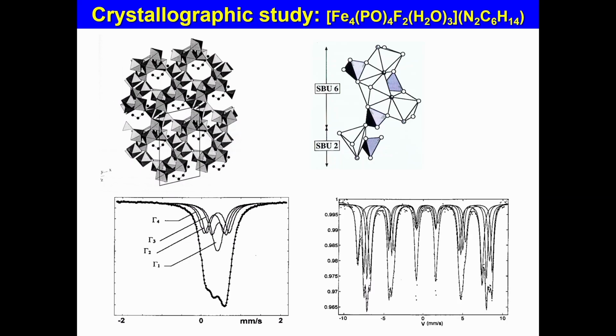Now, some spectra have been done at low temperature. So you can see a change from a quadrupolar structure into a magnetic structure. And it was possible to apply the same strategy with 4 components with different isomer shifts and the same quantities. That means at those 2 temperatures, we are perfectly in agreement with the structure, which has been established from X-ray diffraction.